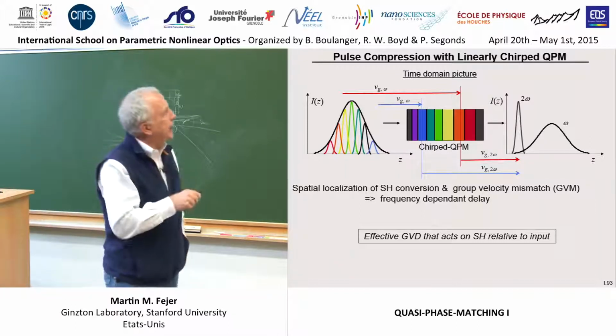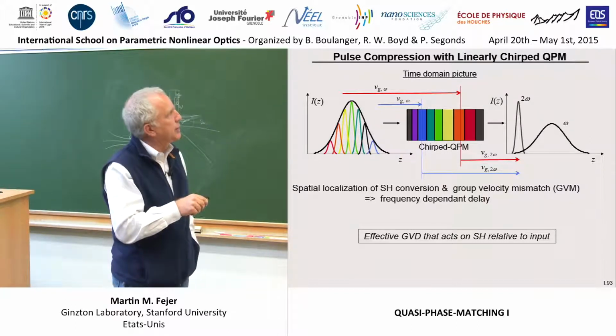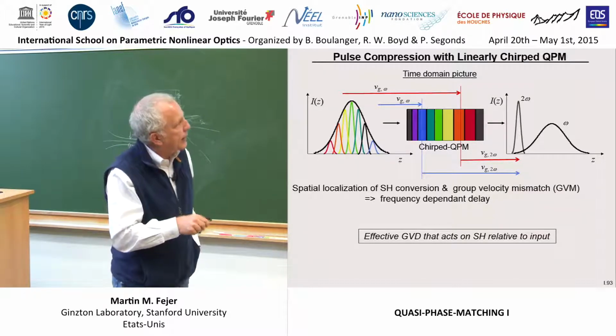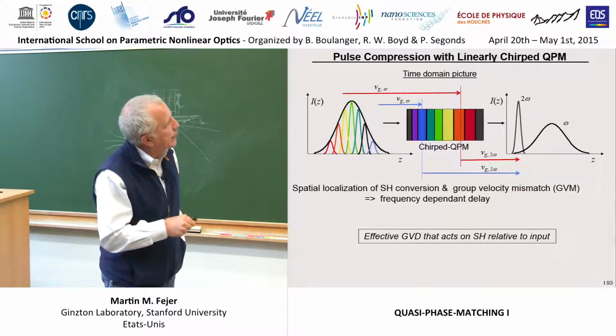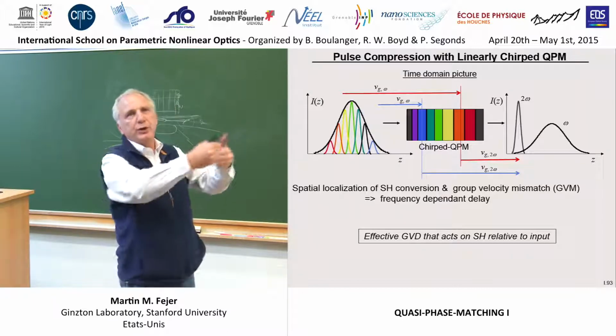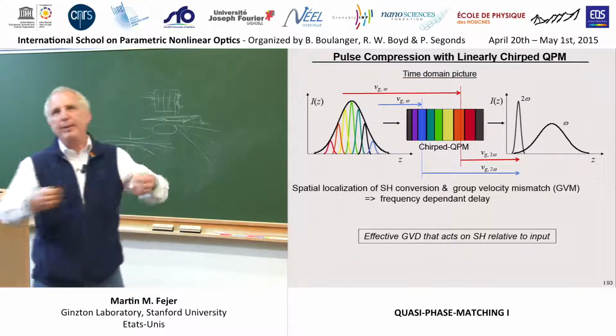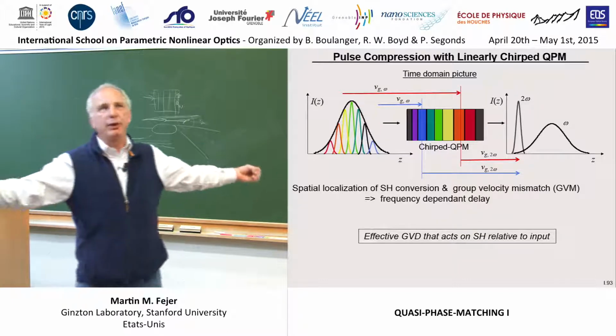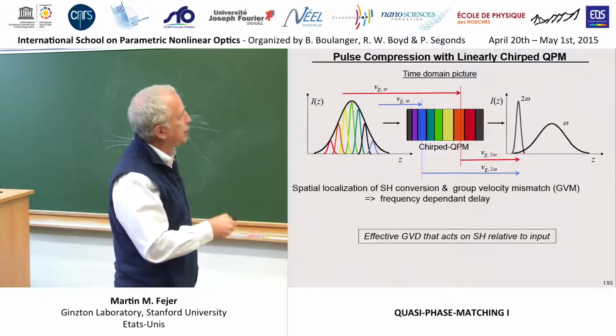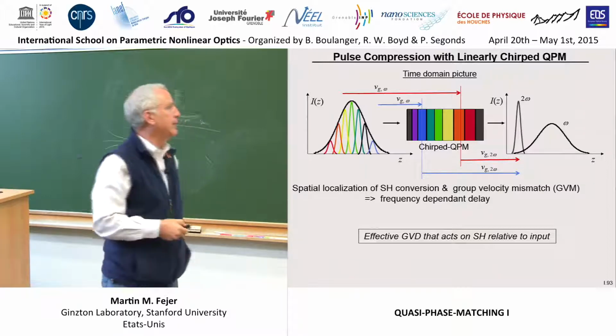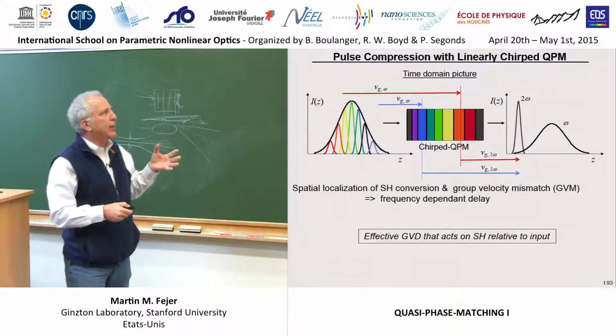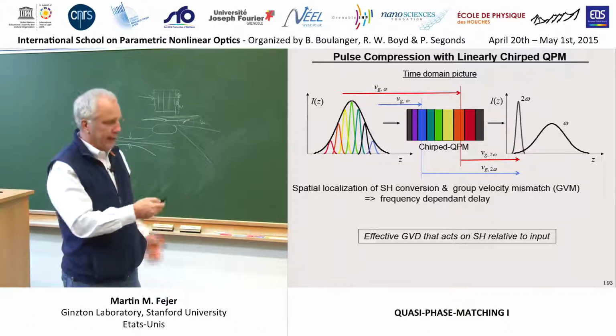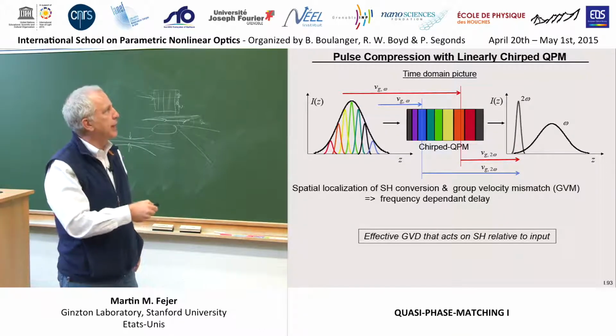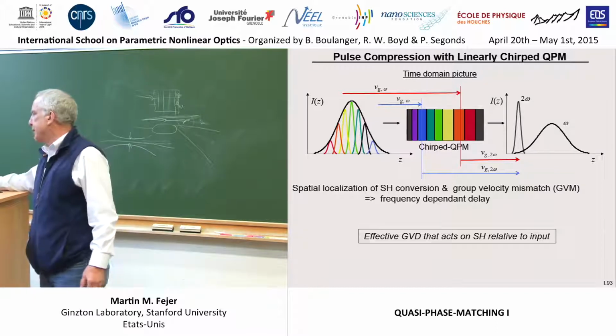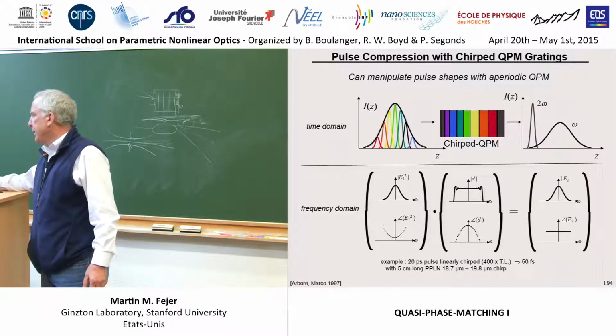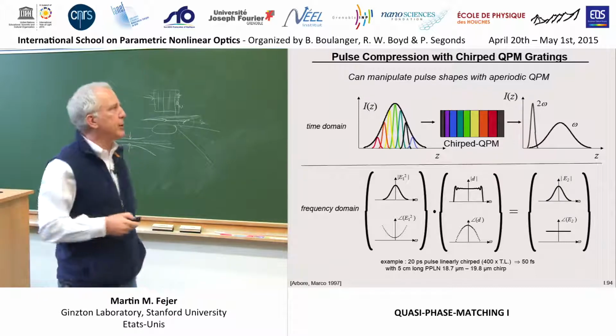So the time delay from when a spectral component enters the chip as a fundamental wave and when it exits as a second harmonic wave is controllable by your choice of the chirp rate of this grating. And you can program in a nearly arbitrary group delay as a function of frequency by your choice of grating chirp function that you put in here. So that's kind of a time domain argument for how you could create, for example, a compressed pulse out of a chirped pulse during second harmonic generation. You could also look at this in the frequency domain.